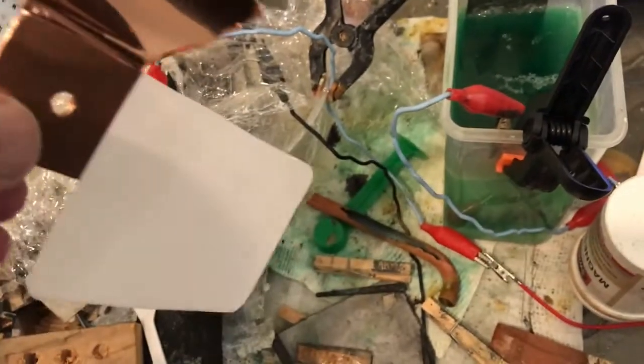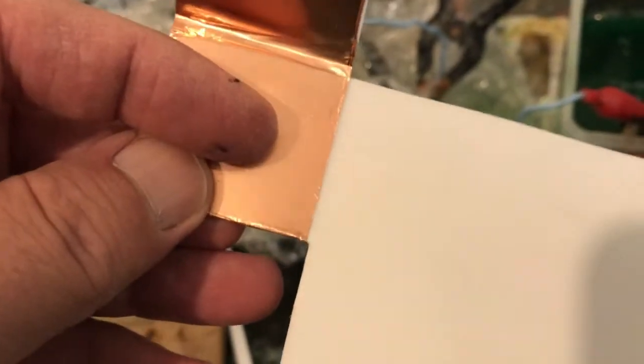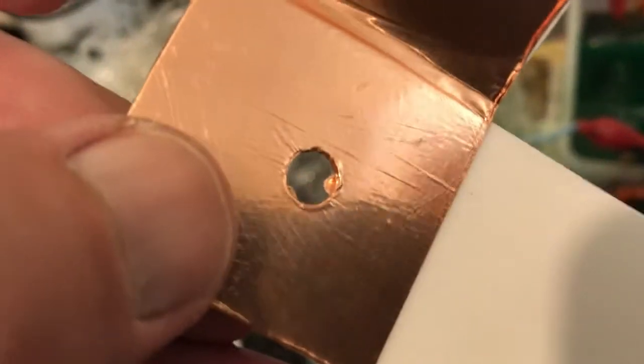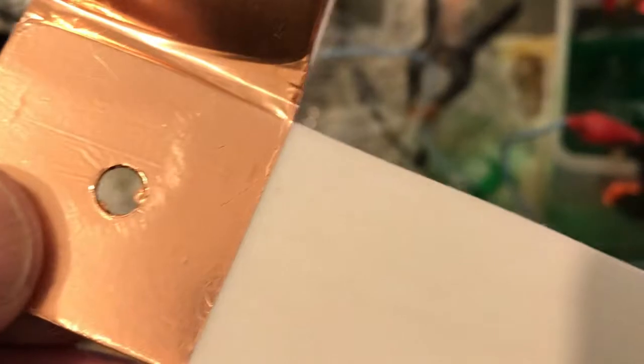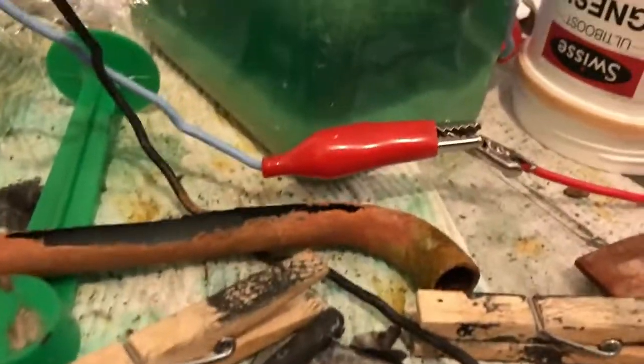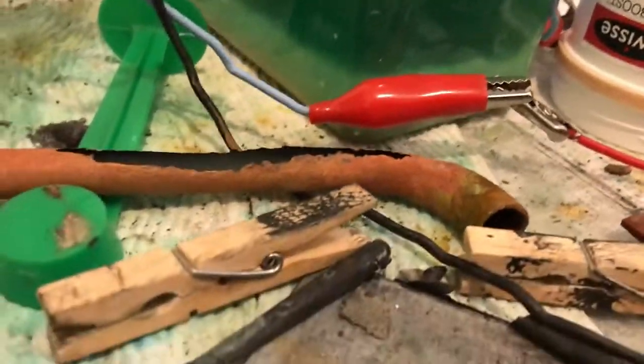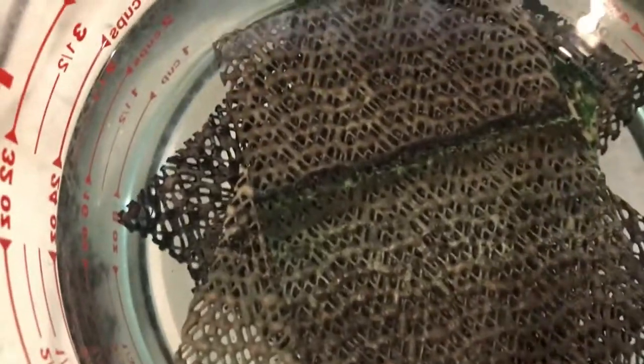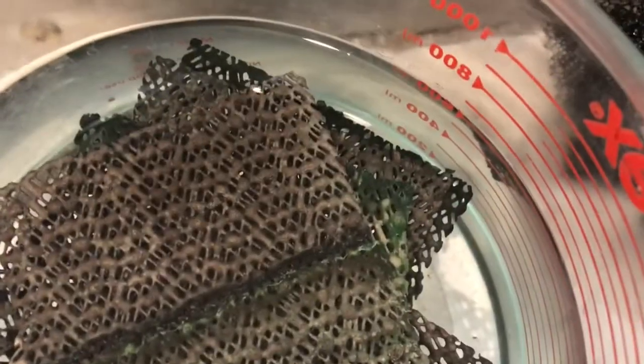You've got to first copper plate them all. When you copper plate it, you can stick it right in. So you want to copper plate the hole as well, and that fills up all the little holes which we've generated and makes a good contact. And then nickel plate it. I'm not sure if my nickel plating is getting contaminated, but see, they're coming out black now, a funny colour, and green bits are coming out. I'm washing them down.